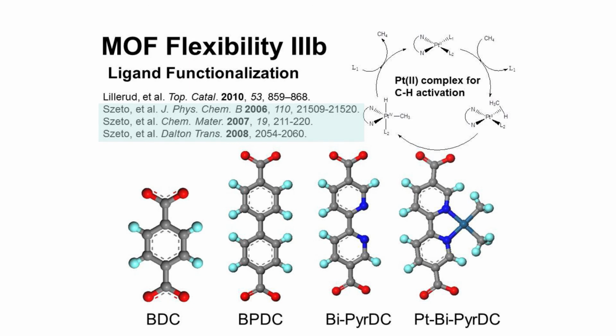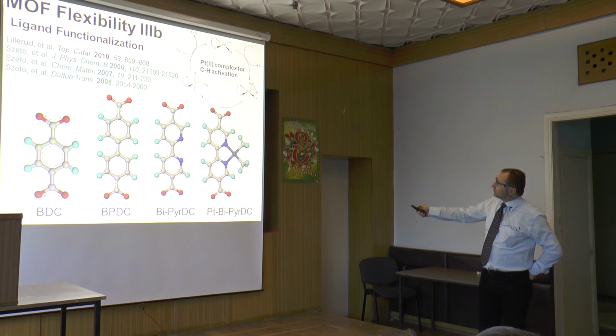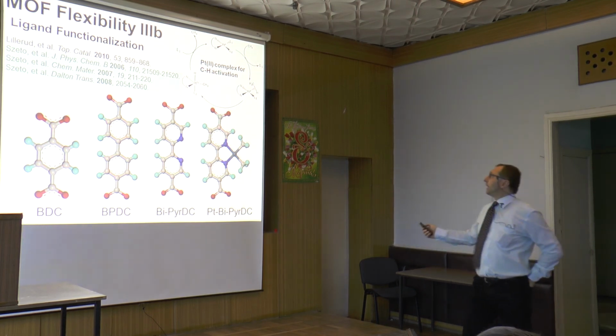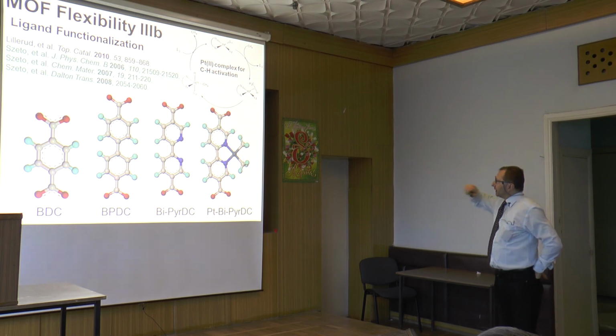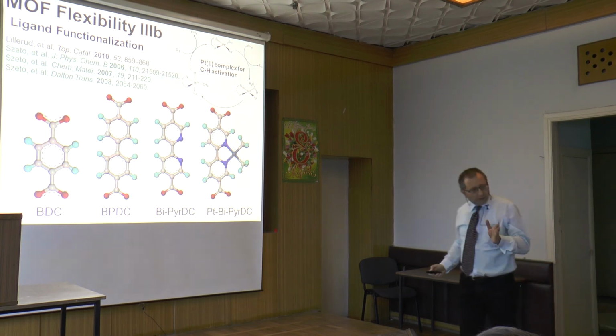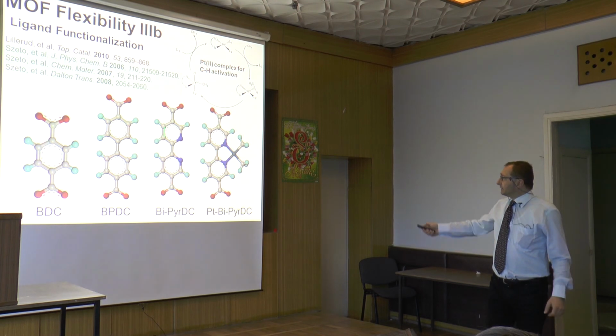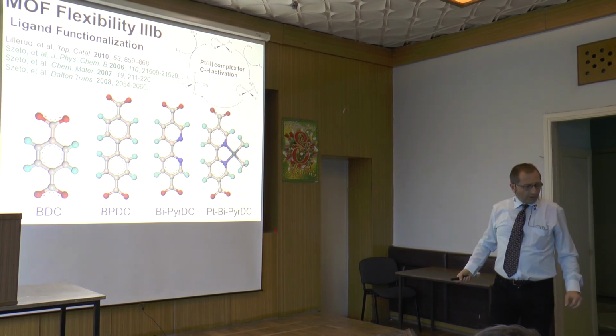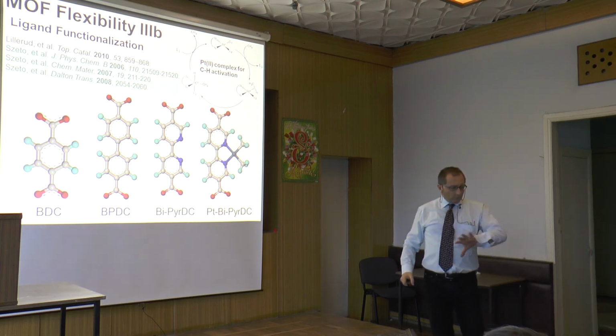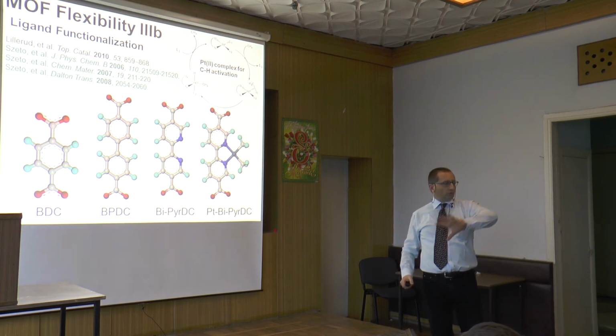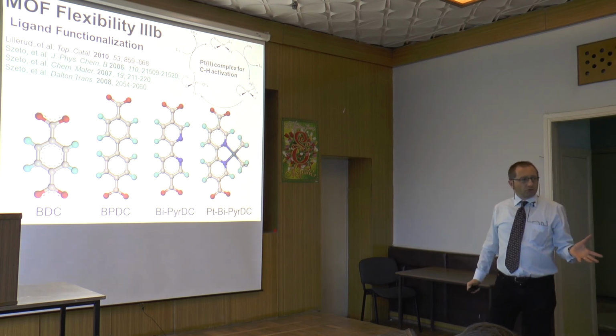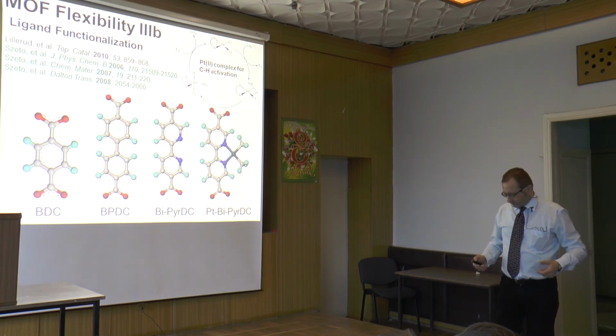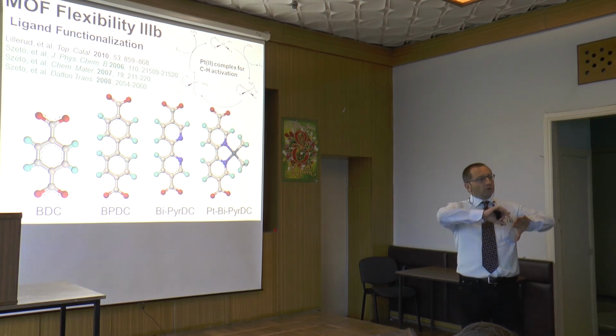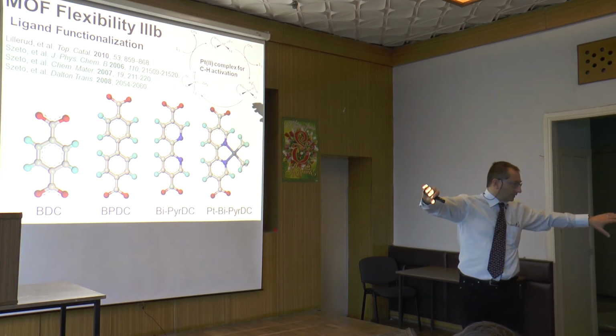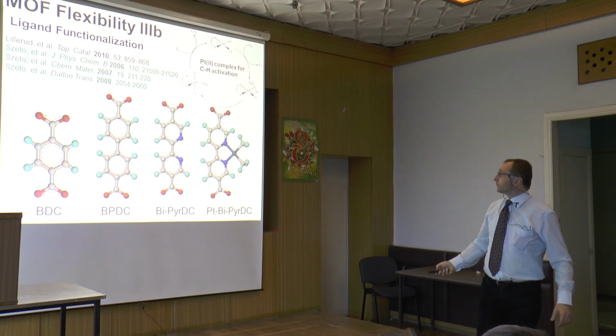And in this particular case, this is relevant because square planar platinum-2 is the most used catalyst in homogeneous reaction for this carbon-hydrogen cleavage reaction. And the idea is a MOF like this could be able in the future to move the reaction from homogeneous to heterogeneous catalysis, which has a huge impact in the industrial chemistry, because at the end of the reaction, you don't have to separate the products from the catalyst, because they are in 2 different phases.